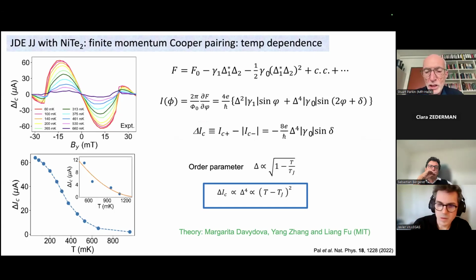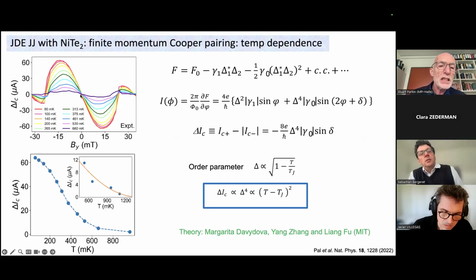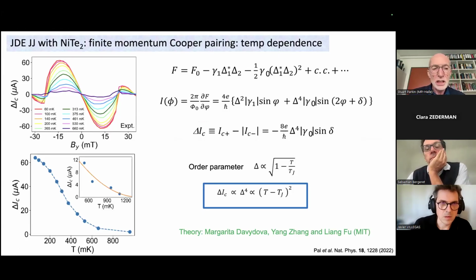And what it means is, when the field is 0, there is no finite momentum. As we increase the field, that momentum will increase. So the electrons, as they tunnel, the Cooper pairs, as they tunnel through the Josephson junction, will pick up a phase. And what is extremely interesting is, as you can see from our experimental data in the top left, here delta IC is the difference between the critical currents flowing to the right and to the left. In zero field, they're the same. As we increase the magnetic field up to a maximum, in this case 15 millitesla, you see that the magnitude of the difference in the supercurrents increases.